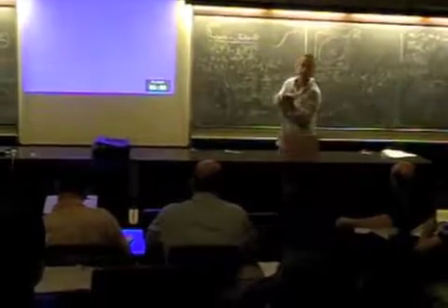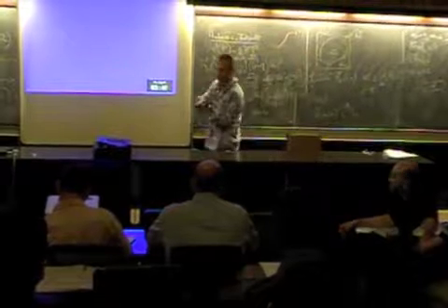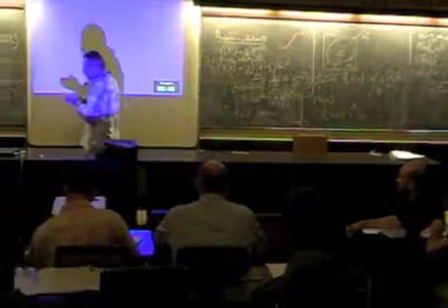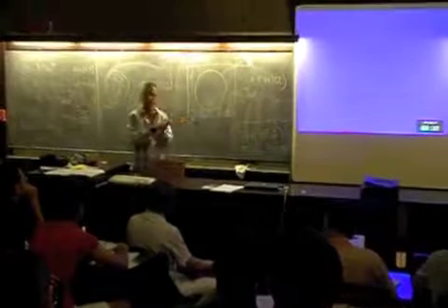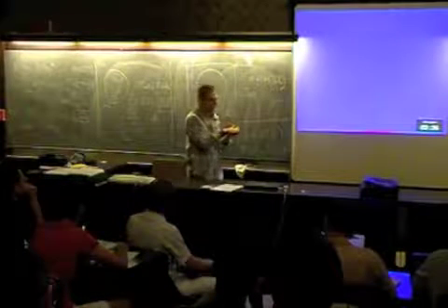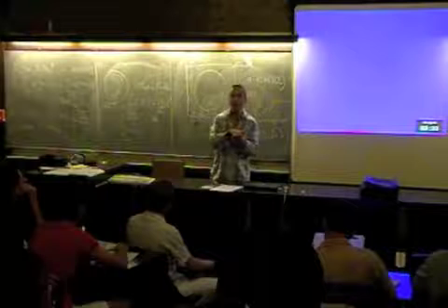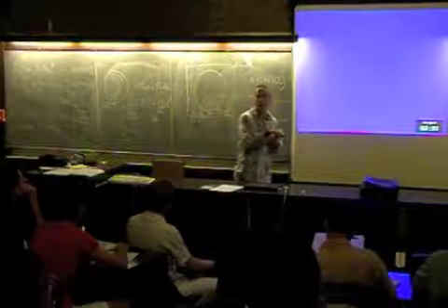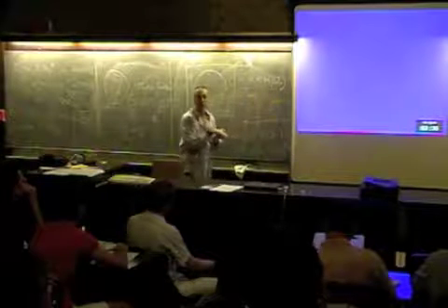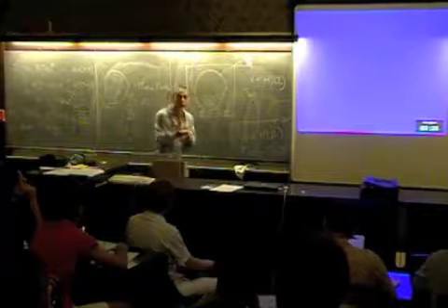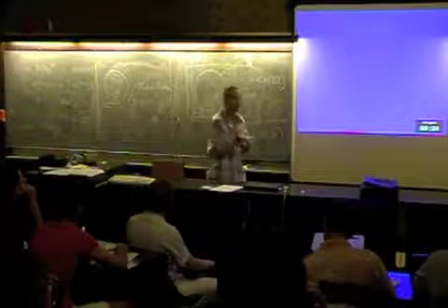So what Sergei is alluding to is the fact that in linear elasticity, in 2D isotropic, it is said, and probably true, although unfortunately Professor Berdichev is not here because he jumped again, that the singularity of the crack tip is in square root of R. That means the stresses blow up like 1 over square root of R, where R is the distance to the crack tip.